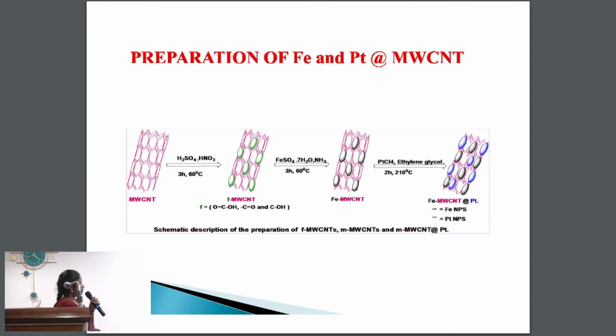Then I take 0.1 molar ferrous sulfate heptahydrate dissolved in 50 ml double distilled water. Then I add 10 ml of ammonia solution. This mixture was stirred for 3 hours at 60 degrees Celsius, and finally I got iron decorated multi-walled carbon nanotube. After that, I take 5 mg of platinum chloride dissolved in ethylene glycol, and this mixture was stirred for 2 hours at 210 degrees Celsius. Finally, I got iron and platinum decorated multi-walled carbon nanotube.